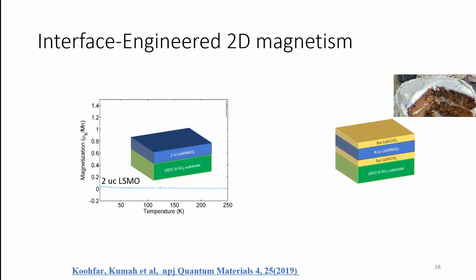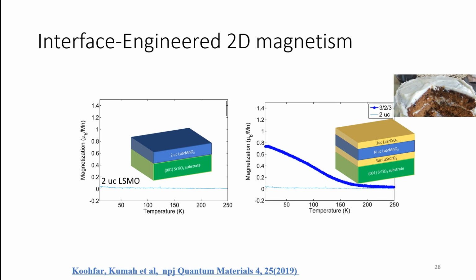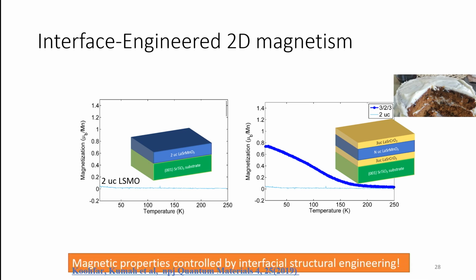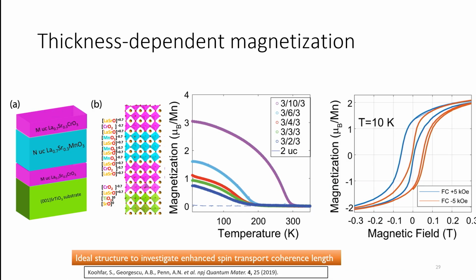Now, if we put some icing on it, so the icing in this case is a lanthanum strontium chromate, we're going to put 3-unit cells on the top and the bottom interface. We do find that the material becomes ferromagnetic. We do now measure a ferromagnetic signal in these very thin films. So again, this is only 2-unit cells of LSMO, and here we're able to find a really appreciable magnetic signal in the sample. So the question then is, why is that the case?